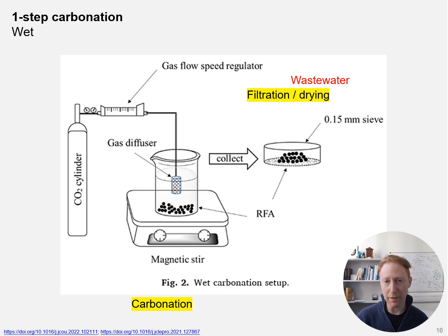For the one-step carbonation process, we essentially put our carbonatable material in water and then expose it to CO₂. So we can bubble CO₂ gas through this solution and the material will carbonate. The carbonated material is then removed by filtration and then dried, and there is also some wastewater to deal with in this process. This is a very simple process.